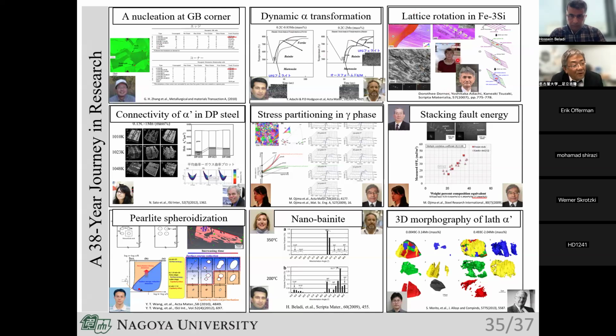And in collaboration with Dr. Dorona, coming from the Max Planck Institute, and also Professor Tsuzaki, in the iron 3% silicon alloy, we analyzed local lattice rotation within the ferrite phases. EBSD helps us visualize the rotation patterns, revealing internal stress and transformation path.